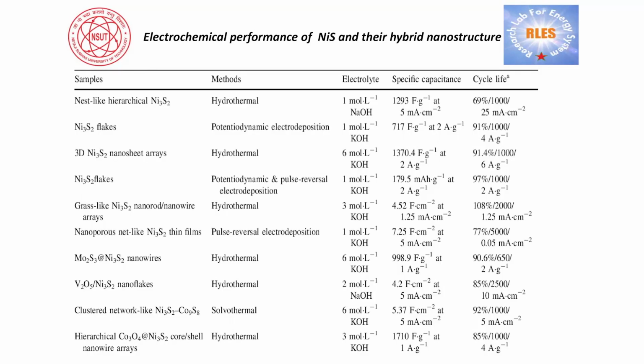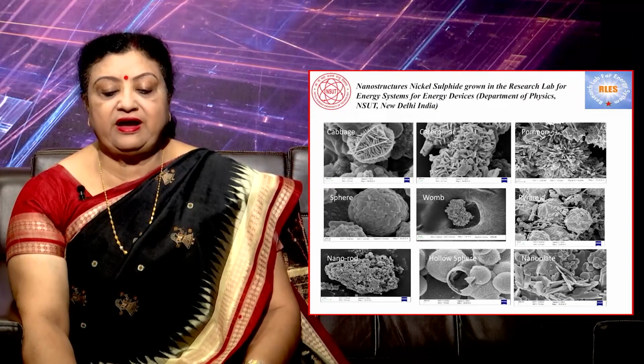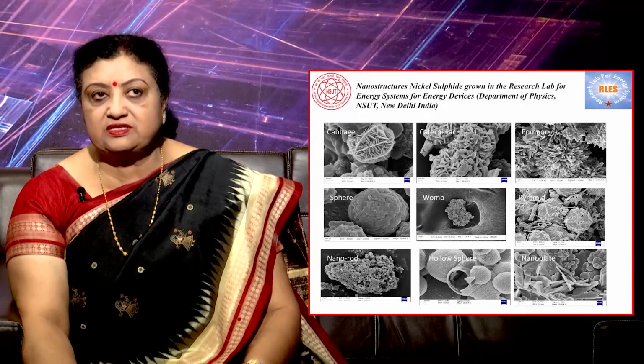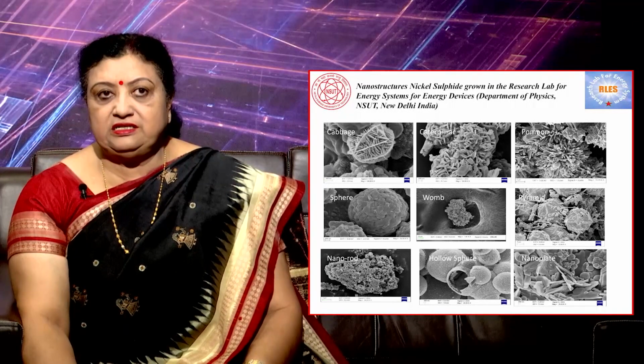So, the samples are nest-like hierarchical Ni3S2, synthesized by the hydrothermal method, Ni3S2 flakes, then 3D Ni3S2 nanosheets, also synthesized by the hydrothermal method. The different samples mentioned here are synthesized by pulse reversal electrodeposition, hydrothermal and solvothermal methods. Nanostructures of nickel sulphide grown in the research lab for energy devices.